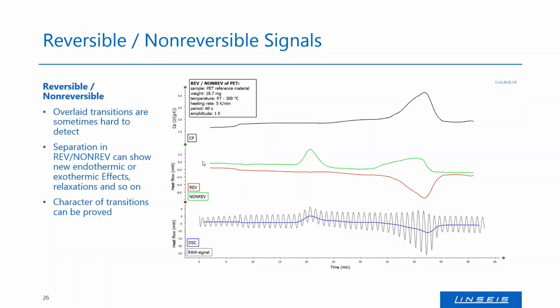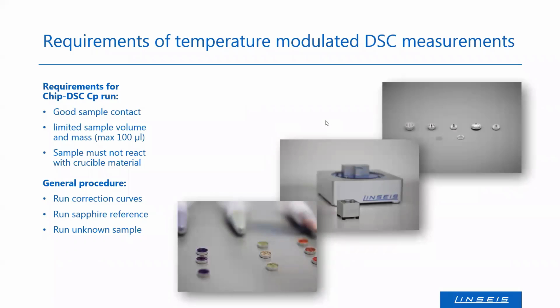Yep, I think I already discussed it with you a slide ago. So there are some things we need for these measurements. The most important thing is that the sample must be able to follow the temperature profile. Especially at lower temperatures near room temperature, or if you use a low temperature option near the lowest possible temperature, it could be hard to cool down because the temperature gradient is pretty small here. For this reason, the first period and, because it's not a complete period, also the last period of a measurement could be a bit strange. You should ignore them. By the way, in our software, they are cut away automatically, so you don't have to mind about it. What's also important is good sample contact, otherwise you cannot get the heat into the sample, and a limited sample volume to avoid temperature gradients.